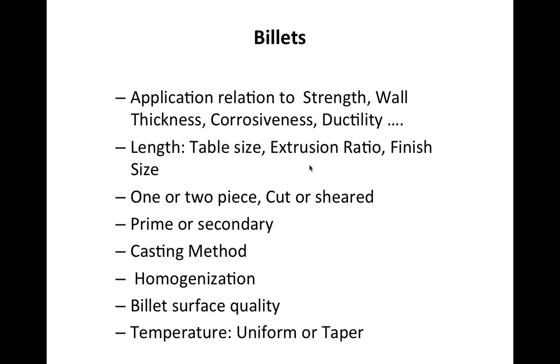Homogenization. I hate to say it, but I was actually at an extruder 2 weeks ago who chose not to homogenize their billet. In so doing, they overheated the billet in their billet oven and left it longer on their conveyor so the billet would have a chance to cool so they could avoid homogenization. Unfortunately, this isn't really a good way to save money or time. They had very little control over the billet temperature, and I would say very little control over the finished product.